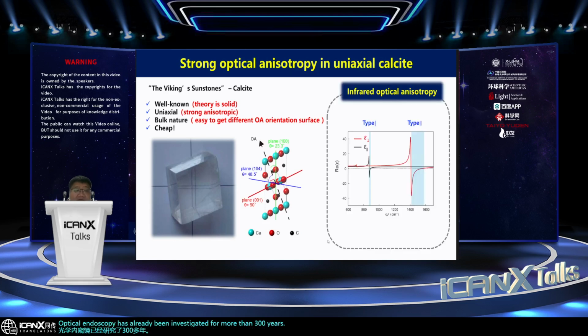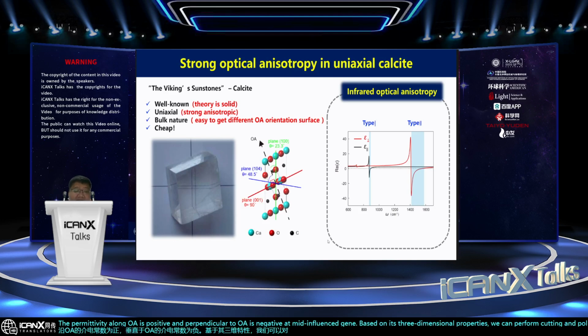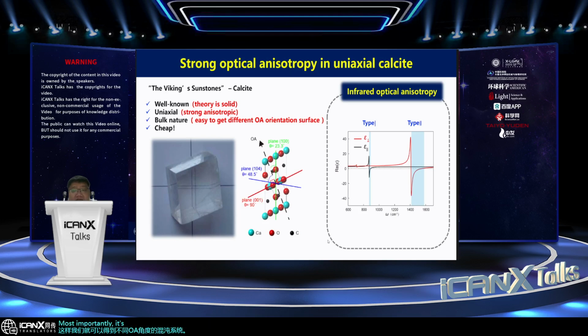The permittivity along the OA is positive and perpendicular to the OA is negative in the mid-infrared region. Based on its three-dimensional properties, we can perform cutting and polishing on it in any direction so that we can get calcite samples with different OA angles. Most importantly, through these tuning methods, we can easily achieve in-plane permittivity sign difference in the mid-infrared region so that we can synthesize the conditions for supporting hyperbolic polariton propagation.